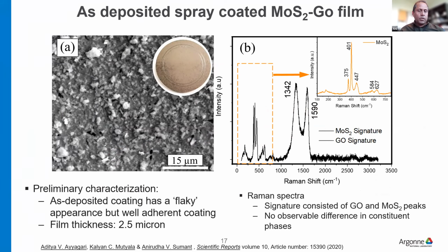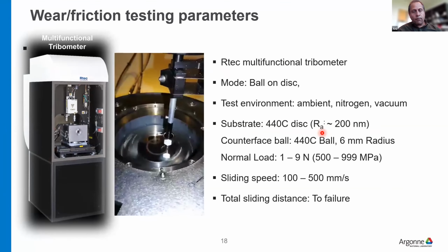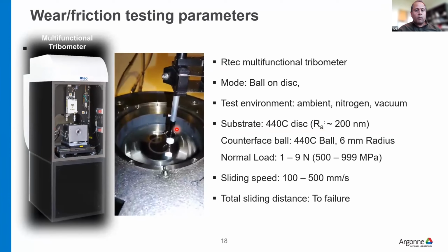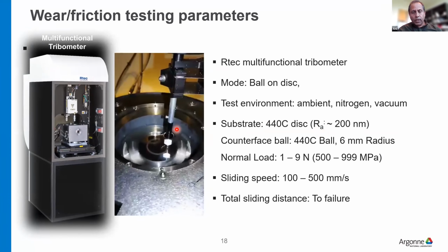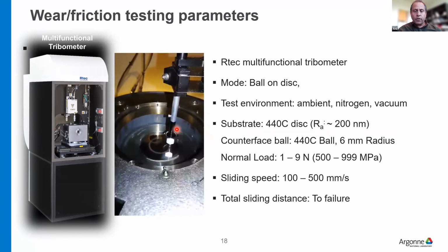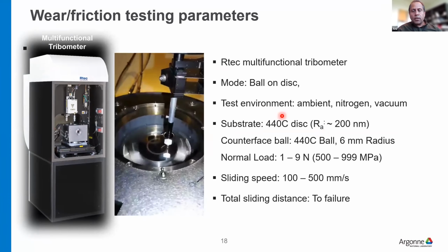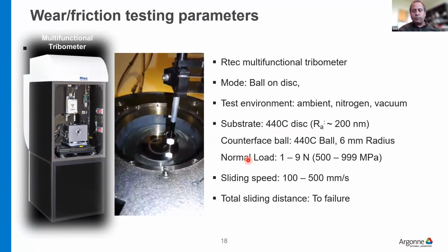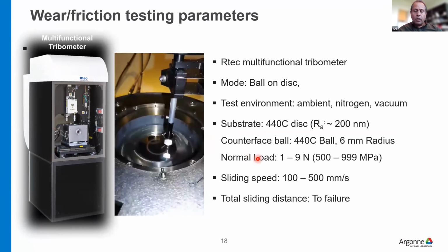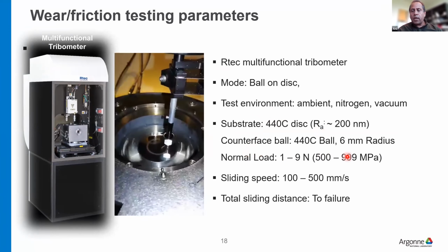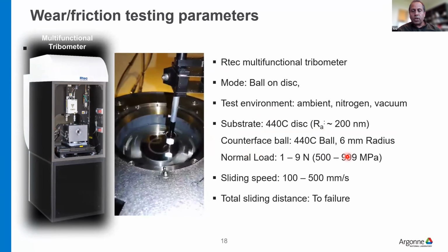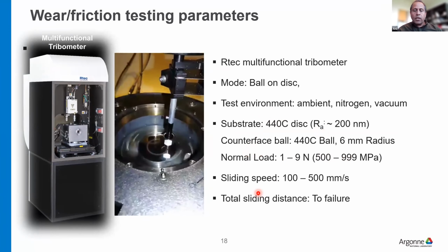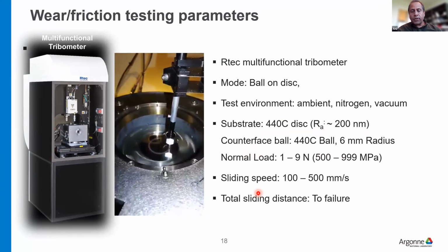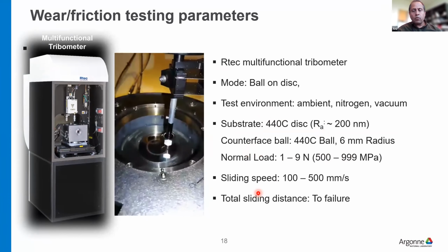And then this substrate is subjected to the tribology test, on a tribometer here at CNM. And these are the typical test parameters with a stainless steel disc, and then the load is going from 1 to 9 Newton. That translates into a contact pressure of up to 999 megapascal, almost 1 gigapascal, and then a sliding speed of up to 500 millimeter per second. In all the tests that we do, we run until it fails.